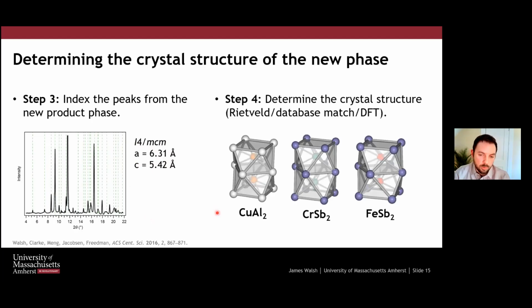And so then the next step would be to solve the phase. And this could be done in many ways. In this case, we find a match to this unit cell to the structure type. And in fact, there are a couple of other phases that are similar, a transition metal and a main group element, that adopt this structure type under pressure. And so it kind of pointed us towards this being iron antimonide.